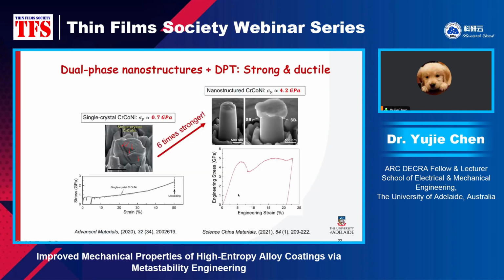So as a result of the hierarchical microstructure and also the dual phase, the chromium cobalt nickel alloy coating that we have developed shows excellent strength ductility synergy. The mechanical performance was characterized by in situ micropillar compression test. As we can see, ultra high strength of 4.2 gigapascal was achieved. What does that mean? We can compare this one with the bulk single crystal sample, which has the same composition. We can see the strength has been increased by 6 times. So it's 6 times stronger. And with such a high strength, the nanostructured chromium cobalt nickel alloy coating still shows appreciable ductility, as we can see from this stress strain curve.